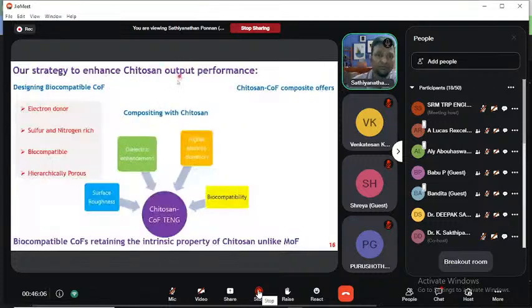This is our strategy to enhance the performance. We want to fabricate a biocompatible composite system. We designed a biocompatible COF which possesses electron donor character, because chitosan is an electron donor. If I use an electron acceptor material, it will neutralize the performance. So I want to add an electron donor material into the electron donor polymer matrix. For this electron donor nature, I intentionally introduced sulfur and nitrogen based ligands, which are biocompatible, so the entire COF acts as a biocompatible material. And as you know, COF material has a hierarchically porous structure, which also helps to retain the surface charges because it captures the surface charge density.